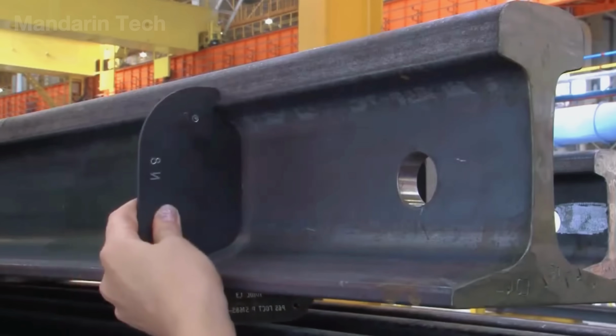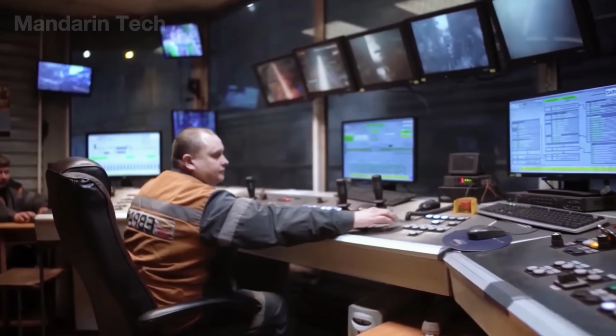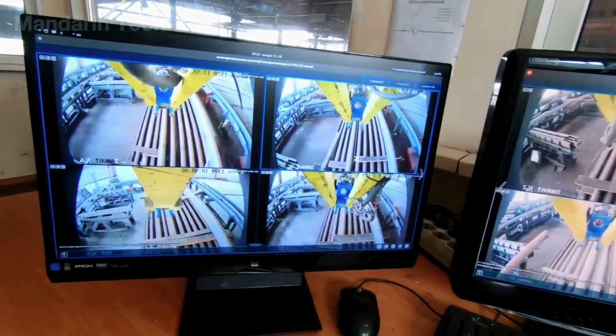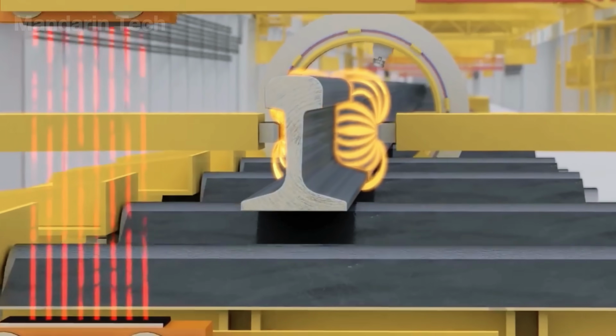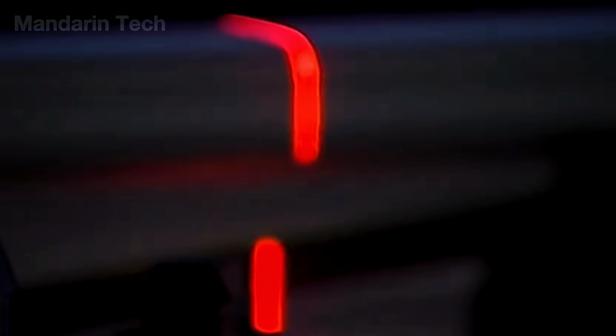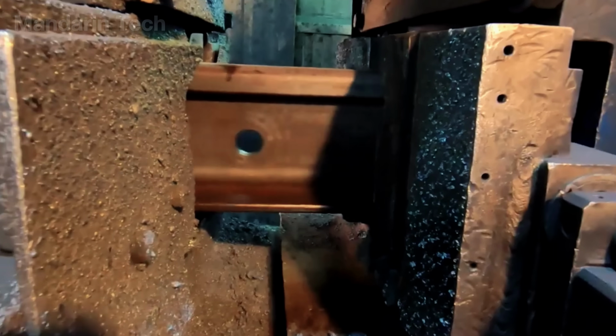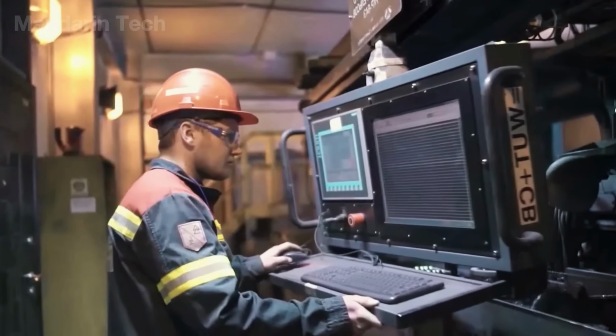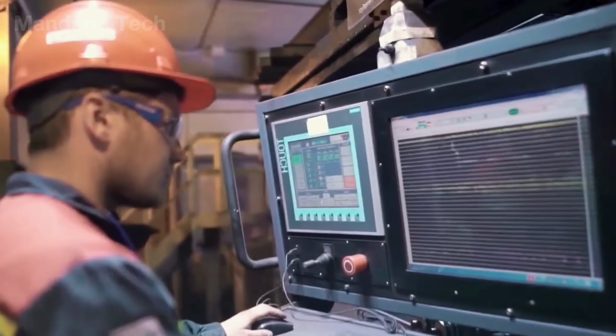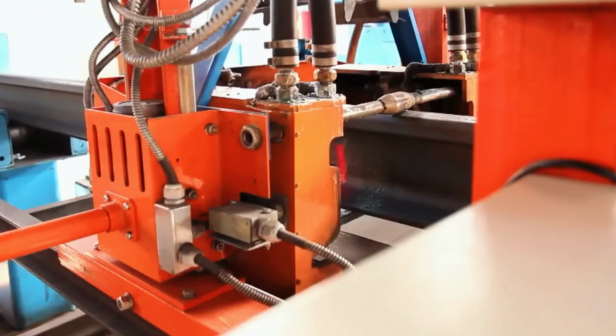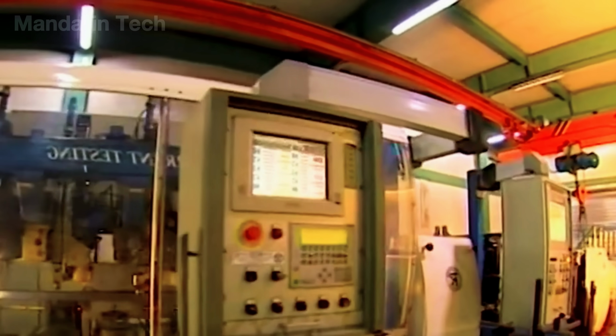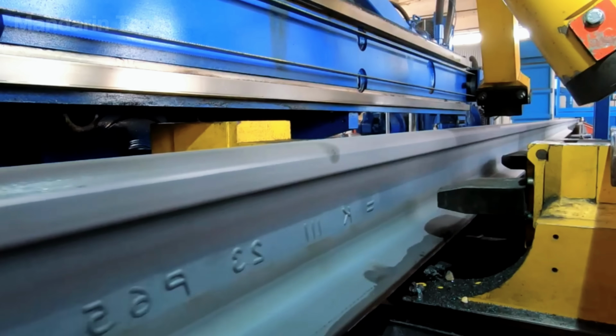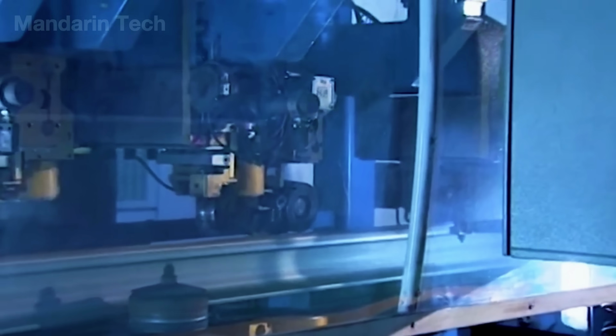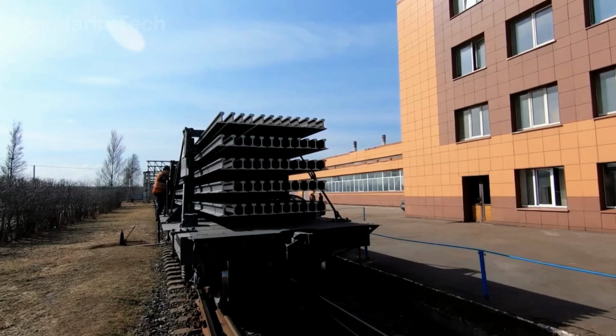The finished rails are then transferred to the automated inspection area, where high-speed cameras and optical sensors scan the entire surface at microscopic resolution. Meanwhile, ultrasonic and X-ray systems examine the internal metal structure, automatically rejecting any rail that fails to meet specifications. Random samples are tested using tensile machines, compression rigs, and Rockwell hardness testers to evaluate load-bearing capacity and deformation resistance. Each rail that passes inspection is laser-marked with a traceable identification code, ensuring full production transparency and consistent quality before shipment.